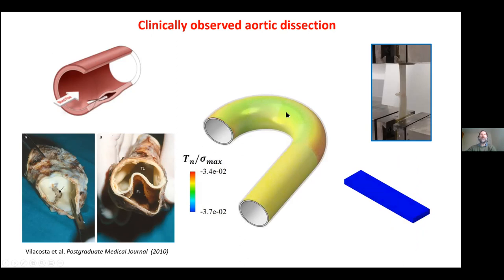But if we simulate an aorta or any blood vessel, as we're doing here, what's the main mode of loading on the blood vessel? The main mode of loading is very high blood pressures, 120 millimeters of mercury, maybe 200 millimeters of mercury, of lumen pressure acting outwards onto the vessel wall. What this means is that the stress component in the radial direction is under compression. Here I'm plotting the tractions, or the forces, along the plane between the intima and the media in the aorta. If you look at this contour plot, all the numbers are negative. It starts at minus 3.4e-2 and goes up to minus 3.7. That's telling me that in the radial direction, the aorta wall is entirely under compression everywhere.